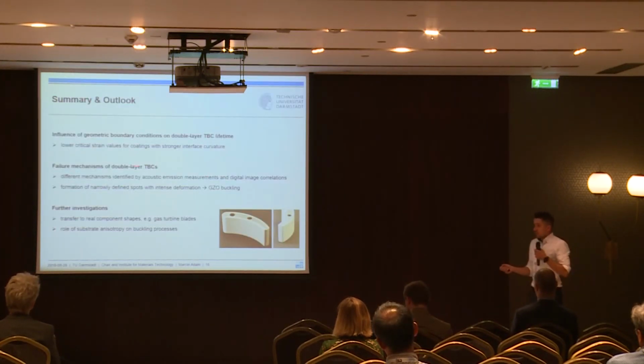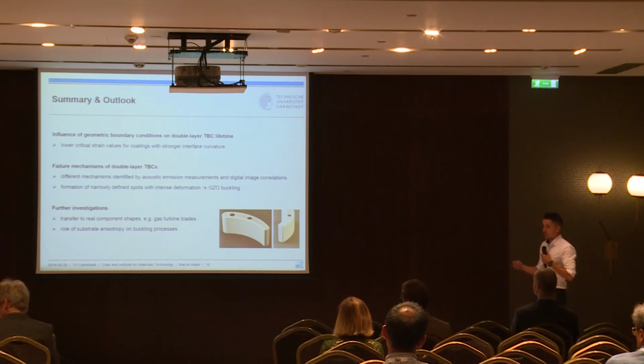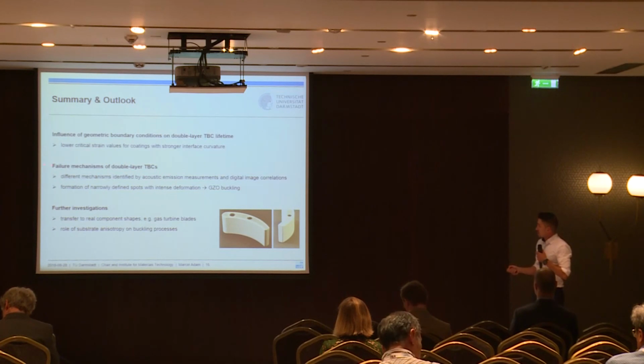So let's come to the summary and an outlook. I introduced you to the concept of double-layer thermal barrier coatings to withstand higher temperatures and to increase the gas turbine efficiency as well. We found an influence of the geometric boundary conditions on the lifetime of those double-layer coatings, and we found that a stronger interface curvature leads to lower critical strain values, so you have a lower strain tolerance. And by studying the acoustic emission measurements together with digital image correlation, we found different mechanisms in those double-layer coatings, and the double-layer coatings started to fail by gadolinium zirconate buckling.